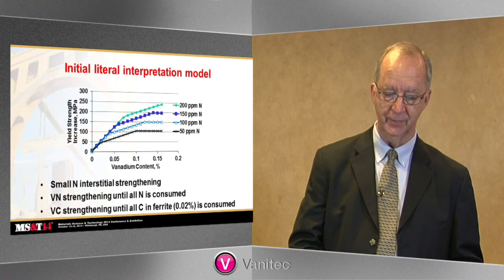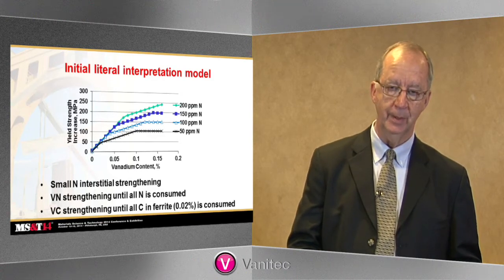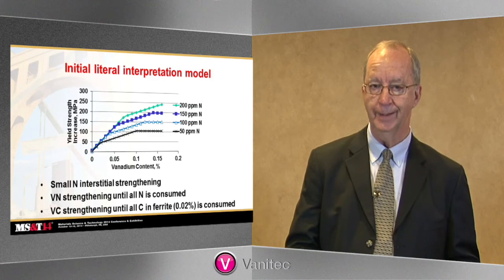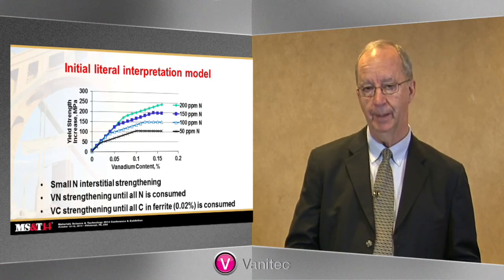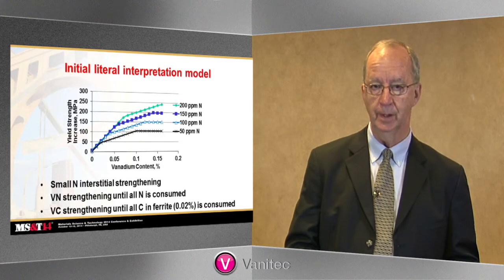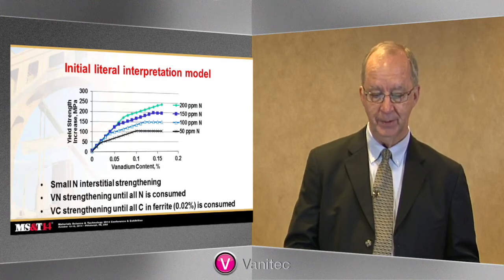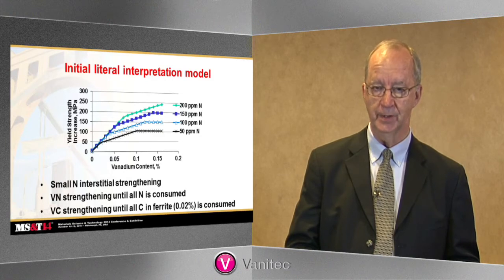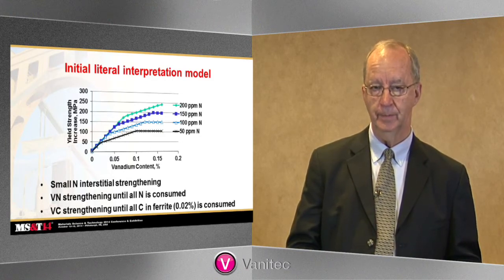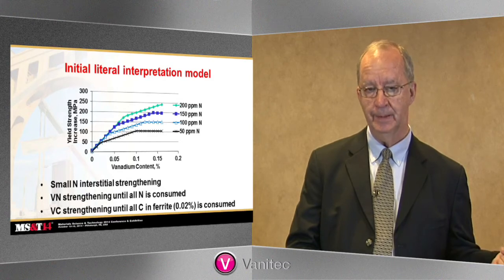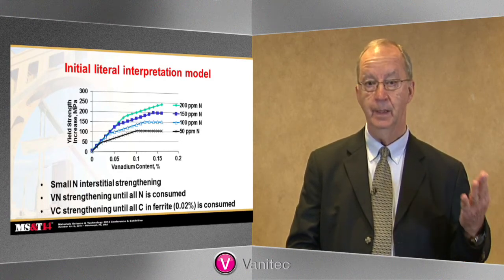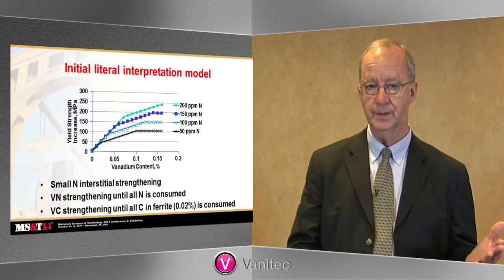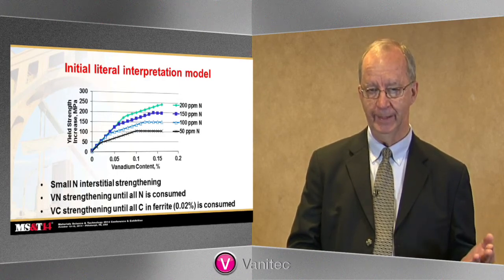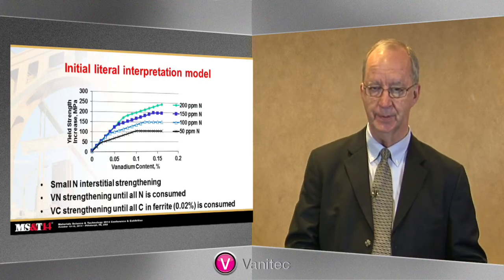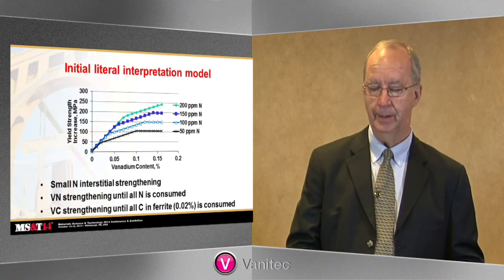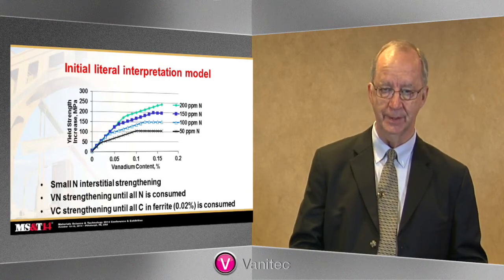The second slope is vanadium carbide strengthening, but we have to remember the maximum solubility of carbon in iron ferrite is about 0.02%. So you can also run out of carbon. So eventually, stoichiometrically, you will run out of carbon as well. So you first can form vanadium nitride, then vanadium carbide, and then there is really no other interstitial element left for the vanadium to precipitate with to contribute to precipitation strengthening. So it simply stays in solution and the precipitation strengthening component essentially stops.